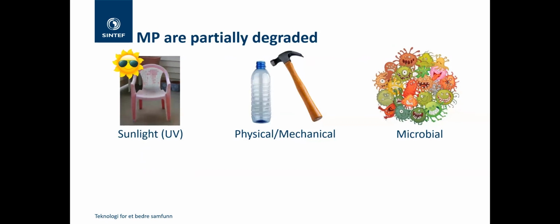But we also know that the vast majority of microplastic particles that we find in the environment are partially degraded in some way. And by this, they fall under the term secondary microplastic, which is plastic particles which are fragmentation or degradation products from larger plastic items, as opposed to primary microplastic particles, like the pellets and microbeads that are added to certain consumer products. Those are micron-sized plastic particles that are specifically manufactured in that size and used for a particular purpose. But most of what we see is these partially degraded particles, and we're starting to get a good overview of the mechanisms that are driving the degradation process.